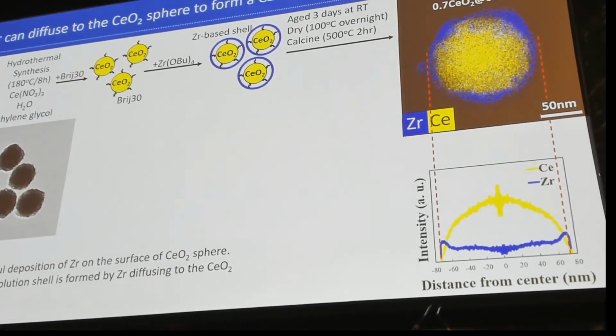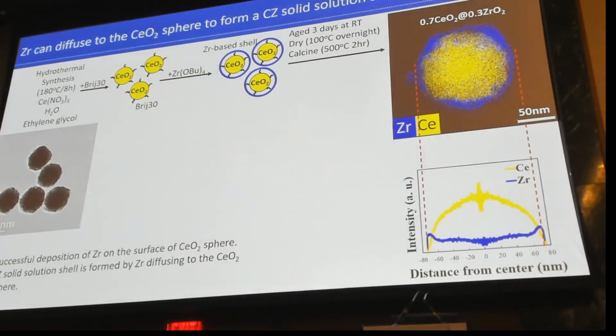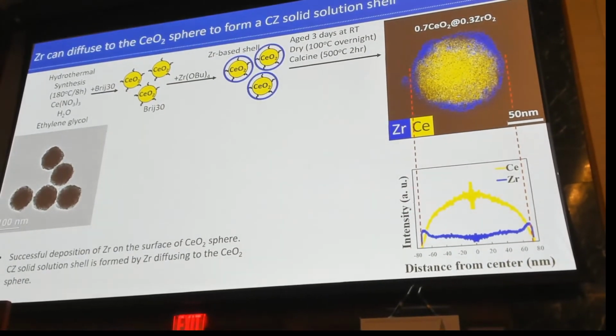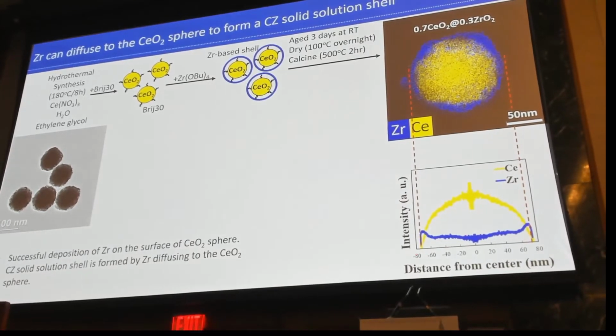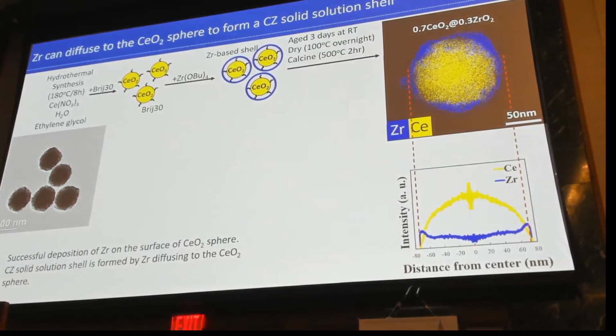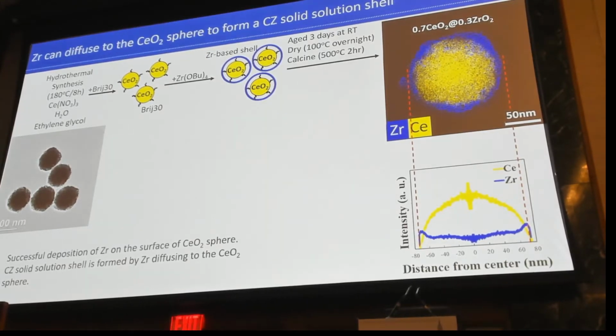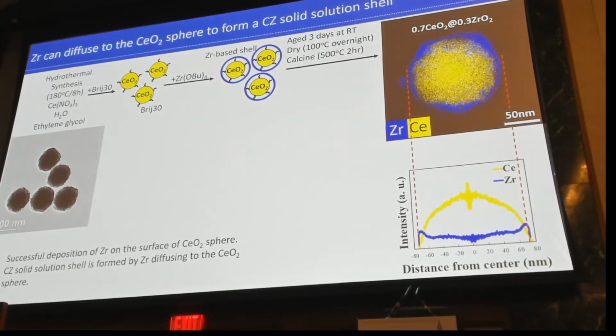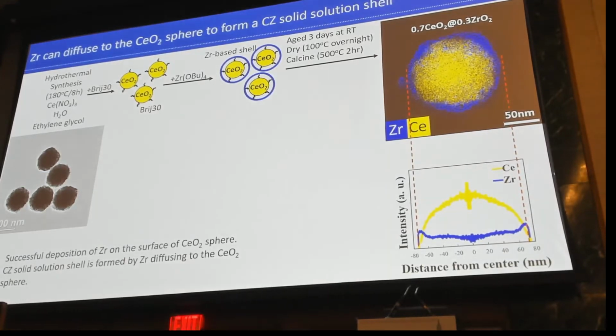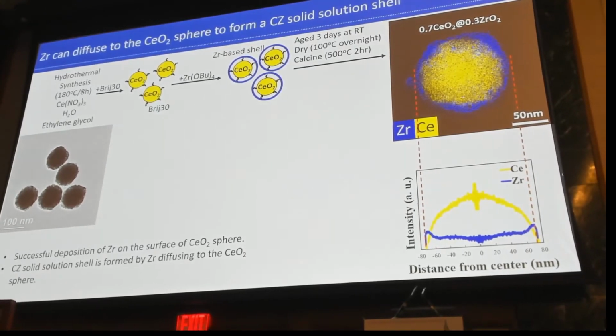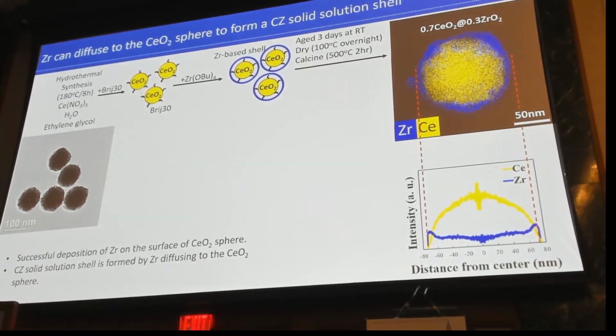So Judy was able to convert the brightness of this EDS image to intensity, and you can see the results here. This is the intensity of cerium and zirconium across the diameter of the particle. What we see is that indeed the cerium intensity is increased in the core, and zirconium has an increased intensity at the ends of this particle, so at the shell of this particle. So what we think is happening is that on the shell we have both cerium and zirconium, and a solid solution is formed.